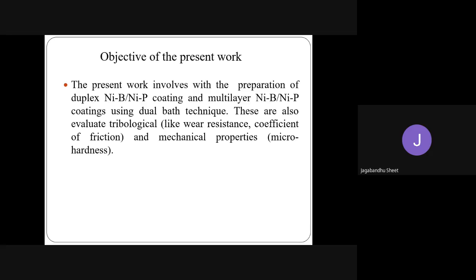And another thing, the multi-layer coatings, NiB and NiP, with four successive layers, are done during the coating deposition process. Like that, NiB as an inner layer and NiP as an outer layer, and also coating using dual bath techniques. These are also evaluated for tribological properties like wear resistance and coefficient of friction, and mechanical properties like micro hardness can be measured here.